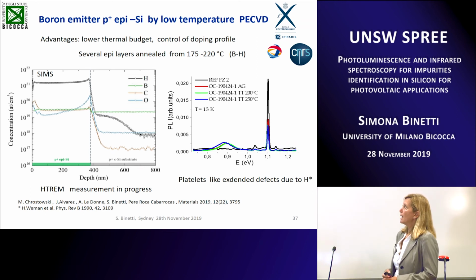and also it's possible to have a very tuned control of the doping profile. But you have to treat the samples afterwards, because you have to activate the boron, which means you have to deactivate the boron-hydrogen complexes, because you can see by secondary ion mass spectroscopy that you have in this material a lot of hydrogen, boron, oxygen, and carbon coming from the precursors of boron in plasma enhanced chemical vapor deposition. And they have seen some not very good lifetime in this material after this process.